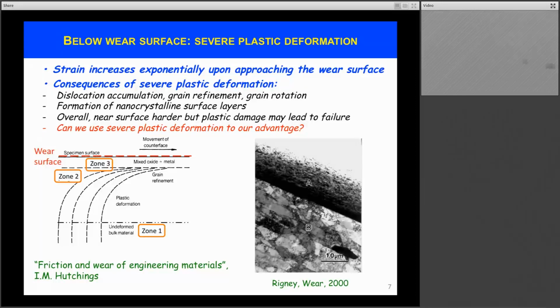So the wear surface is depicted here with this red dotted line, and what one sees is that typically the strain increases exponentially as one goes from the bulk and approaches the wear surface. This increase in plastic strain has many consequences. So we'll see dislocation accumulation, grain refinement, and even grain rotation as we approach the wear surface, say going from zone 1 to zone 2.